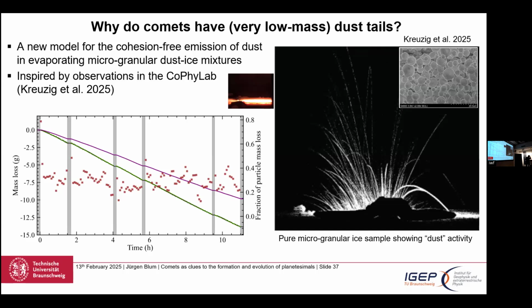So what we started with is pure ice. We made an artificial comet in the lab that consisted of micrometer-sized ice grains. We can produce them in large quantities. So here's the scale. This is 20 microns. The average diameter of an ice grain is 5 microns. It's fluffy, very fluffy, and shiny white. So we brought them into vacuum and shone some artificial light onto it. And to our surprise, we just wanted to take that as a calibration measurement. To our surprise, I hope you can see it, it becomes dust active. There's no dust inside, it's just ice.